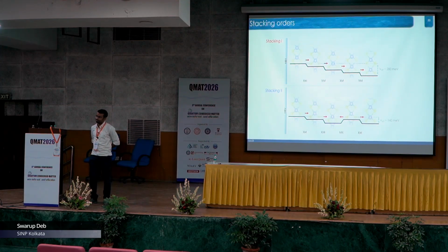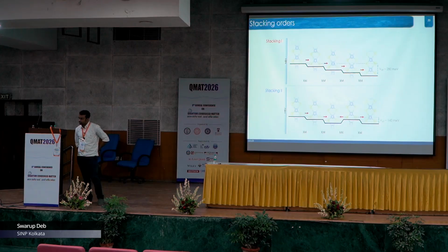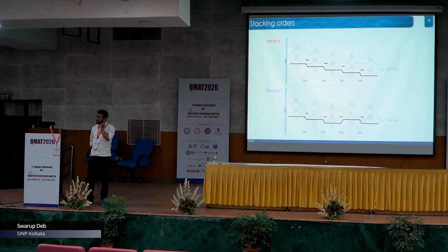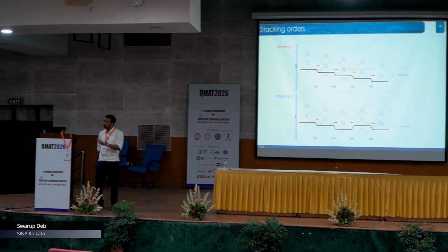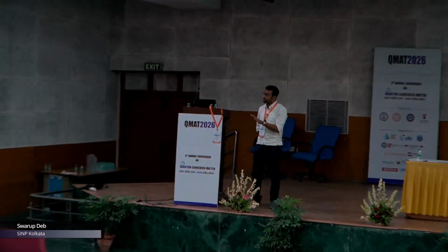Sorry, I don't know if you mentioned this: did you do second harmonic generation? No, not in these measurements, but when we first bought this 3R MoS2, we were skeptical whether it is at all 3R. So the experiment that we did was second harmonic generation, and we get an n-squared dependence with thickness, instead of this odd and even oscillation. So we do know that it's 3R.